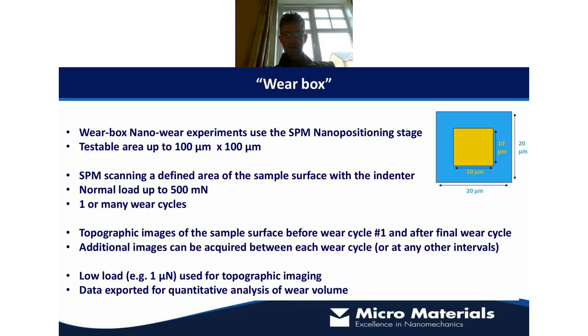Okay, so this is again something new to us, something I did a long time ago in my previous job in AFM, which is to do essentially a wear box test, where you can have a highly loaded region and then a topographically scanned region, and this allows you then to differentiate that height map between these two regions. So this wear box module now in Platform 5 has been developed with as much flexibility as we can think of, so we can perform any range of different combinations of wear cycles and topographic cycles.